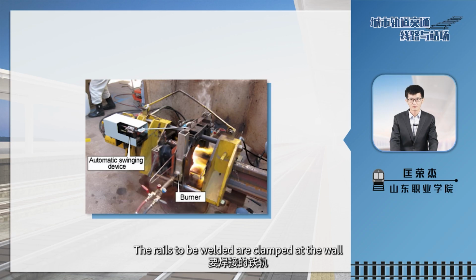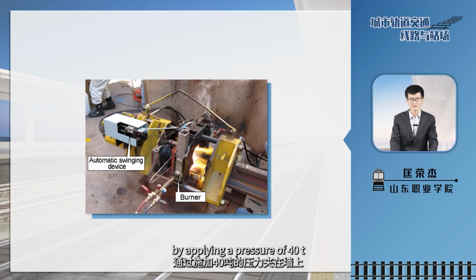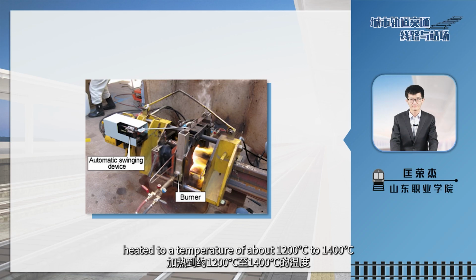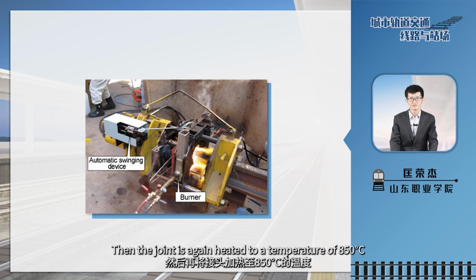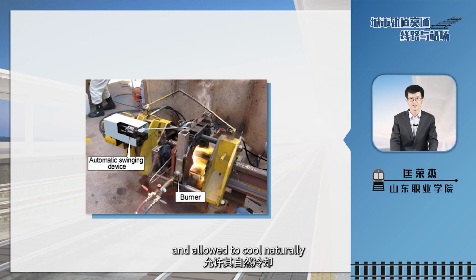The rails to be welded are clamped at the wall by applying a pressure of 40 tons, heated to a temperature of about 1,200 degrees Celsius to 1,400 degrees Celsius, and upset with the opposite pressure of about 20 tons. Then the joint is again heated to a temperature of 850 degrees Celsius and allowed to cool naturally.